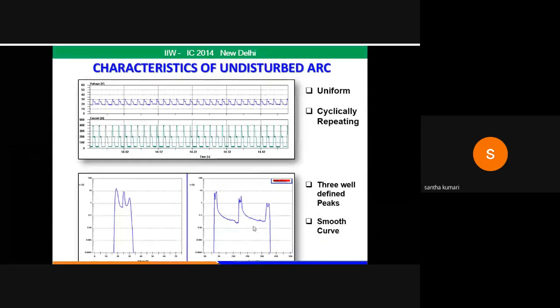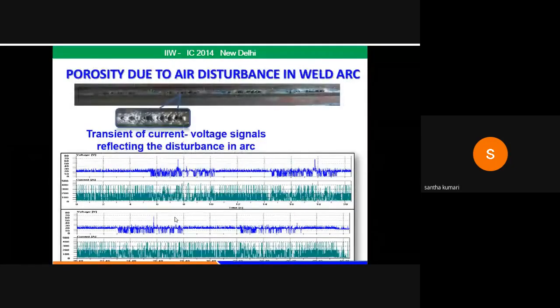So now we tried the burn through defect. I'm not showing that picture here; since I took a lot of time, I have to reduce the time. I'm just skipping the burn through defect detection here. Experiments were actually conducted for burn through and porosities for studies. Here the signatures are obtained by inducing porosities due to atmospheric air, and the arc disturbance is shown here.